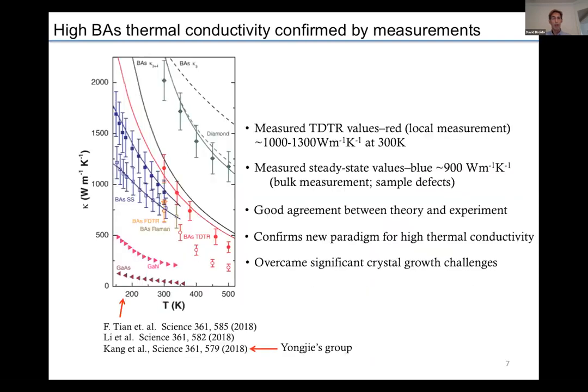So these predictions of high thermal conductivity for boron arsenide have now been verified in 3 separate recent measurements. Yongjie will talk about his group's work next, and the group that I was involved in is the first listed paper, and the thermal conductivity versus temperature is presented in the plot. It's a busy plot, so please focus on the red points, which give the measured time domain thermal reflectance thermal conductivity values. And these are quite high values that are measured. So at room temperature, this high 1300 watt per meter Kelvin value is in fact confirmed by the measurements and in agreement with the theoretical calculations given by the red curve.